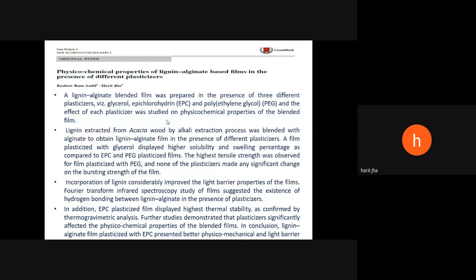Further studies demonstrated that the plasticizers significantly affected the physicochemical properties of the blended film. Now, in this work, we concluded that the lignin alginate plasticized with EPC presented better physicochemical and light barrier properties, which could be used in packaging and coating applications.